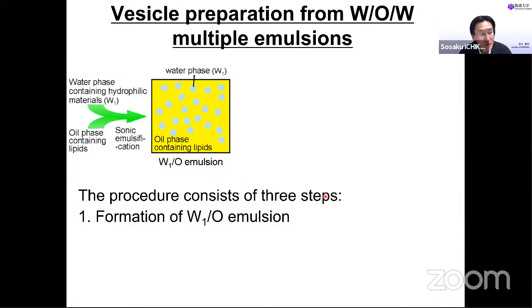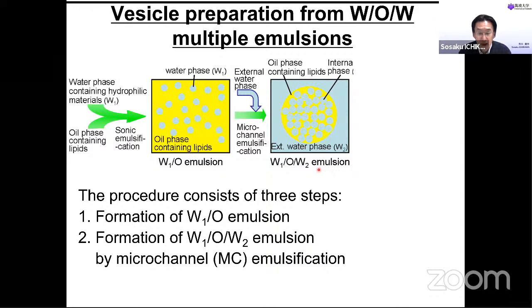This is the step to prepare the lipid vesicle from W/O/W emulsion. Firstly, we mixed water phase containing hydrophilic materials with the oil phase containing lipid to make a W/O emulsion, water droplet in oil emulsion. The hydrophilic material exists in this water droplet. Second, we make a W/O/W emulsion like this. This W/O emulsion is dispersed in aqueous phase to get oil droplet containing this small water droplet. This is a W/O/W emulsion.